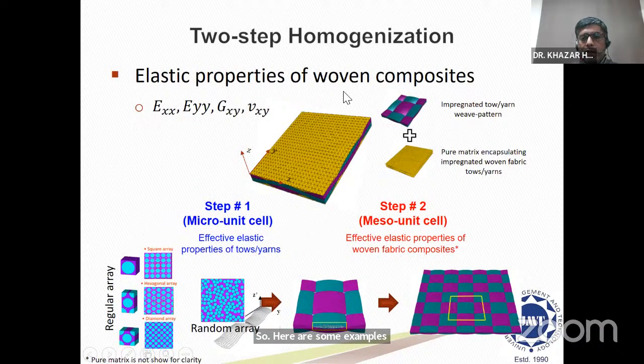So talking about the methodology, how we typically evaluate the elastic properties of woven fabric is shown here. There are 4 elastic properties typically needed for design of a composite structure: in-plane stiffnesses and in-plane Poisson ratio. To estimate these in-plane properties, we do 2-step homogenization. In the first step, we do homogenization at the micro unit cell. We have fiber and matrix properties. From these properties, we estimate the properties of the tow or yarn of a woven fabric composite. And then we add geometrical parameters in the meso-unit cell, and finally we estimate the in-plane elastic properties of the woven fabric.